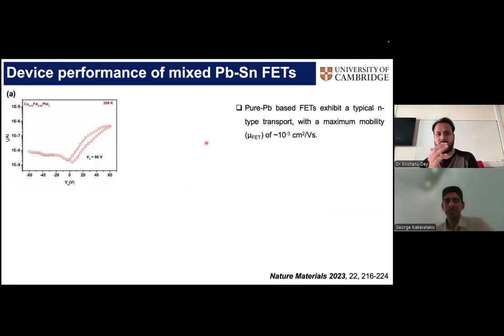So I started to go from pure lead perovskite and then to pure tin, or at least tried to go there. What happened is that if you look at the pure lead perovskite, this is how the transport looks. You can see that the current increases when the gate voltage goes to the positive axis. When the gate voltage is positive, you are basically inducing a lot of electronic carriers to come to the surface, or interface with the dielectric, which we call the channel. So this increase in the current is driven mostly by the electrons, and that's why you call it n-type transport. And we found that the maximum mobility is about 10 to the power minus 3 centimeters square per volt second.